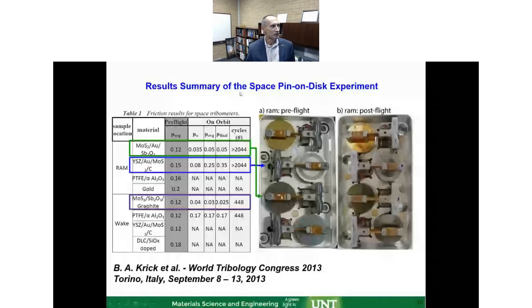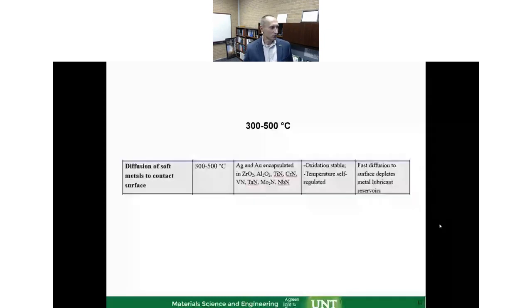And it was in orbit for this duration, a little bit longer than we expected. And when this came back, we had the ability to analyze and compare before the flight and after the flight. And we have a number of coatings there, including these chameleon coatings shown here. And the chameleon coating showed excellent performance across this space test. And therefore, that answers the question engineers in aerospace always ask: was it flown in space? And we can answer, yes, it was flown in space. It showed very good performance compared to some of the baselines, and this is how to get space qualified. And Brandon Krick presented these results at the World Tribology Congress in 2013.